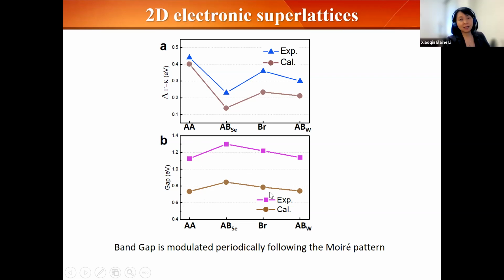Calculations done by DFT are not expected to match the experiment in absolute value, because the fundamental challenge is to define what the band gap is in those calculations. The important thing is they also replicated this trend, how the local band gap changed from one point to the next. And the amount of change is very similar to the experimentally measured value. So this gives us confidence.